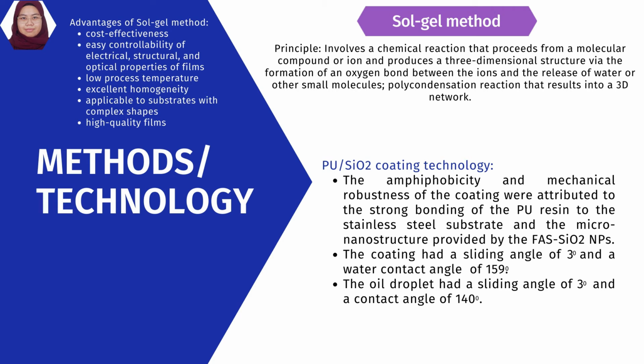For polyurethane silicon oxide coating technology, the amphiphobicity and mechanical robustness of the coating were attributed to the strong bonding of the polyurethane resin to the stainless steel substrate and the micro-nanostructure provided by the fluorosilane silicon oxide nanoparticles. The coating had a sliding angle of 3 degrees and a water contact angle of 159 degrees, while the oil droplet had a sliding angle of 3 degrees and a contact angle of 140 degrees.